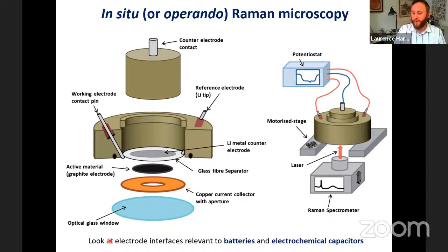But certainly if you're doing very high charge-discharge rates, particularly in supercapacitors, this configuration is probably not optimal. But if you just want to look at what happens to these materials under potential control, or whether we see any sign of intercalation, then this is a reasonable experimental setup to take. As I say, it is a porous electrode. It's not like a uniform barrier where you have to wait for some solid state diffusion to pass through. We really have micron or submicron particles where you could argue that the electrode-electrolyte interface is even at the backside.